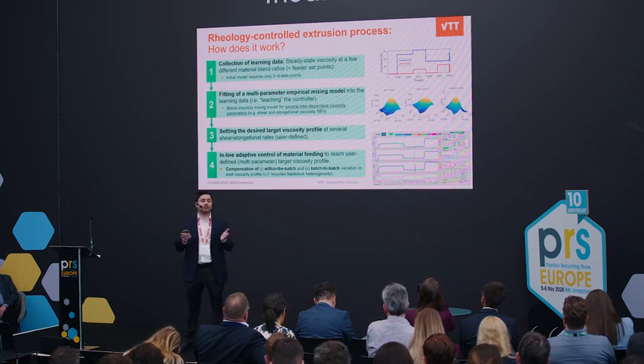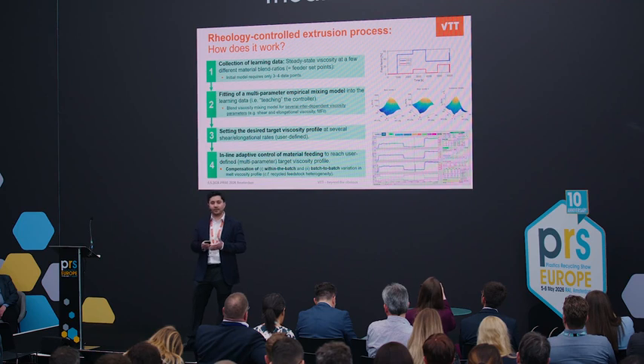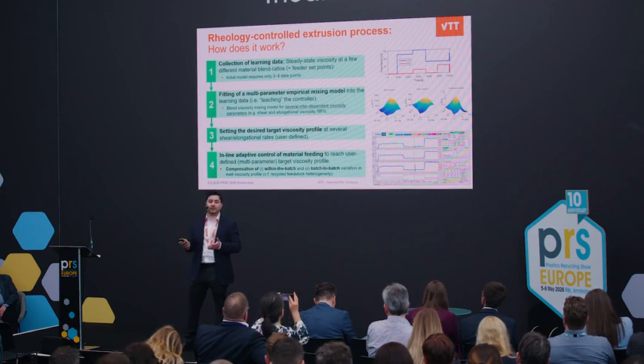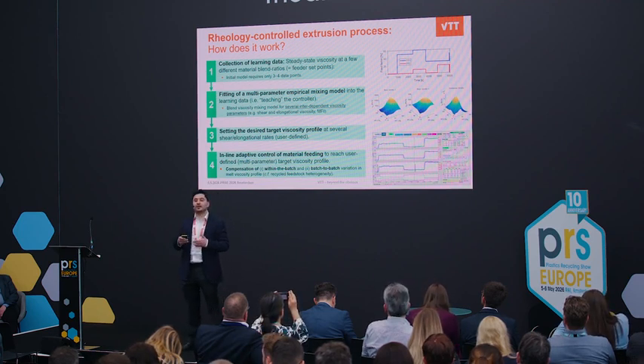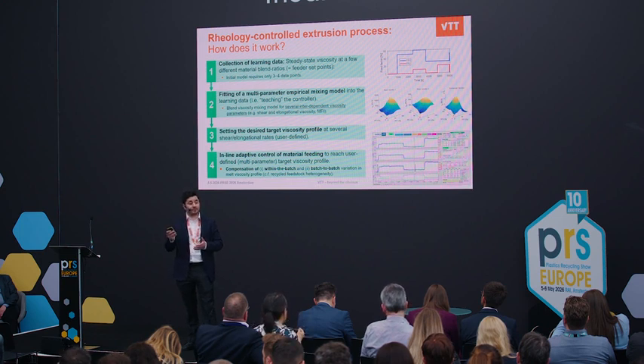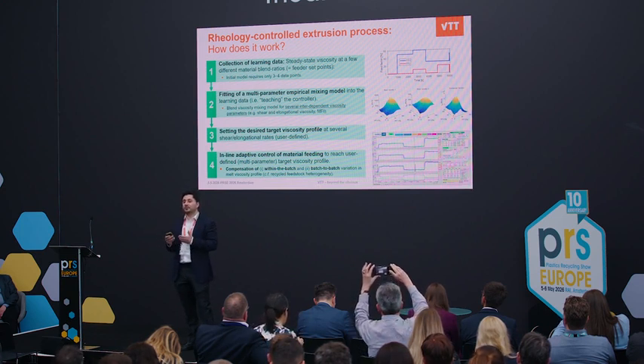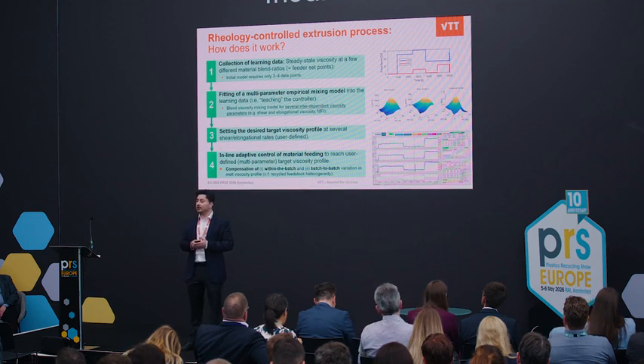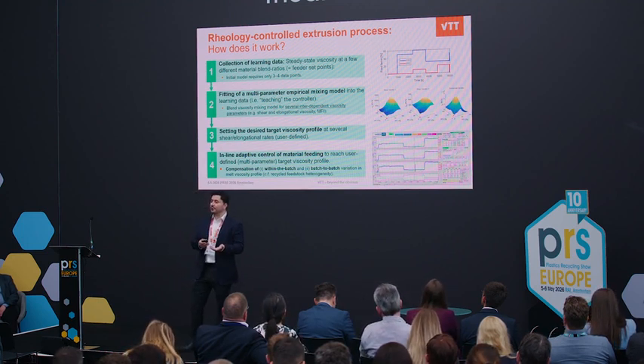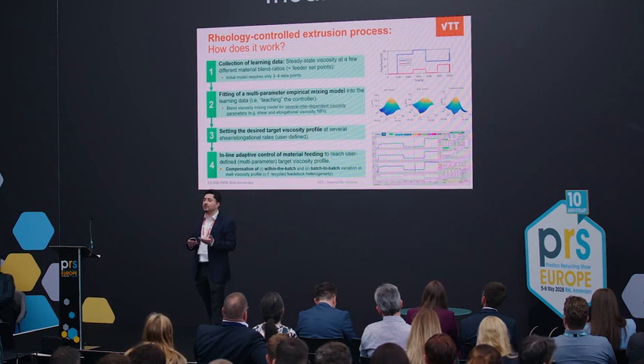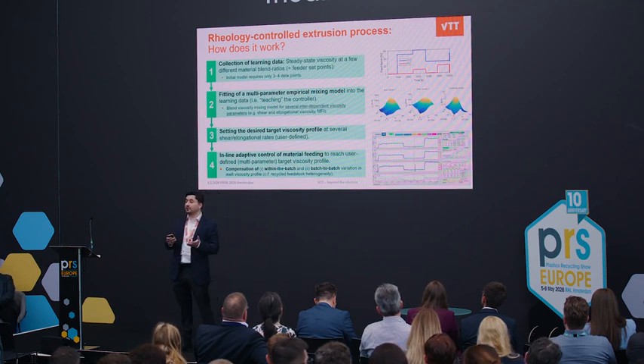So if you would like to reach 10 MFI of a polypropylene, but it's fluctuating between 8 and 15, then you first teach the material to the equipment, and you have your other additives, other polymers with the same chemical composition, but with different MFI levels. So the equipment will tell you how much you should add to reach a certain viscosity level.